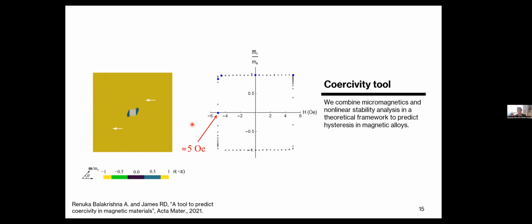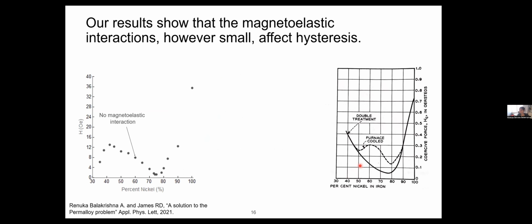So we use this framework to test if we can help understand the interplay between material constants when we think of the Permalloy problem. And so what we do is, when Bozorth and Walker measured the different coercive forces as a function of nickel content in iron, they not only predicted the coercive force, but also measured its fundamental material constants.